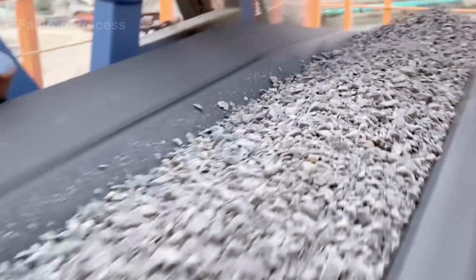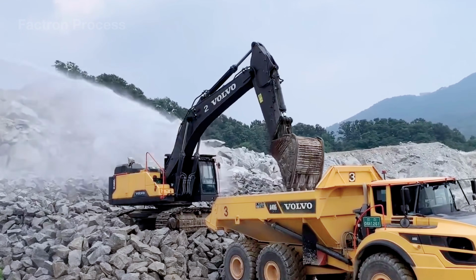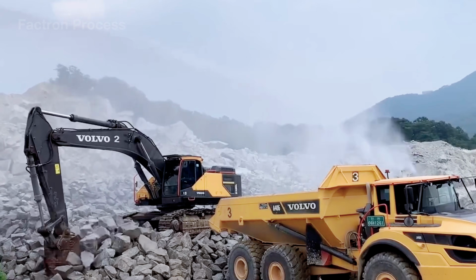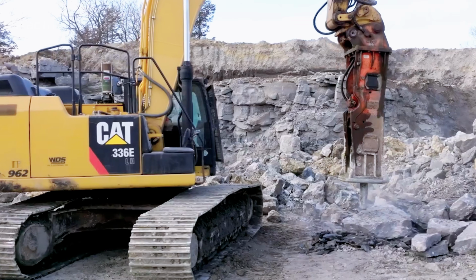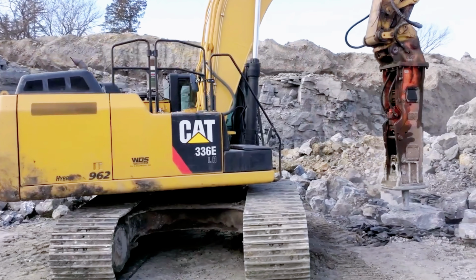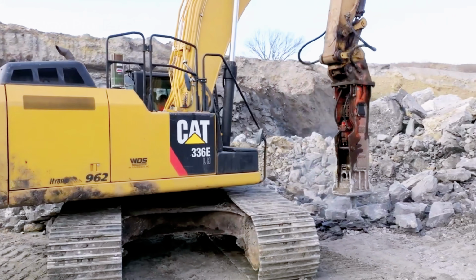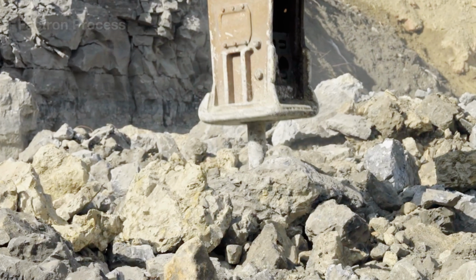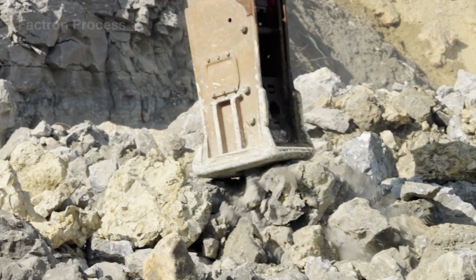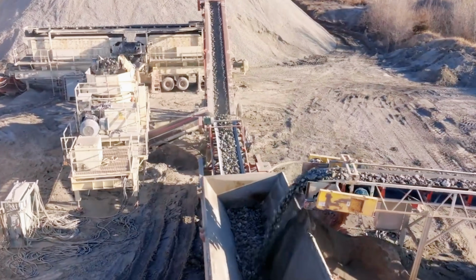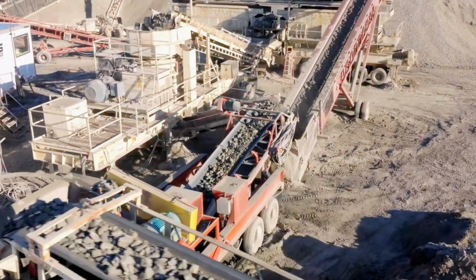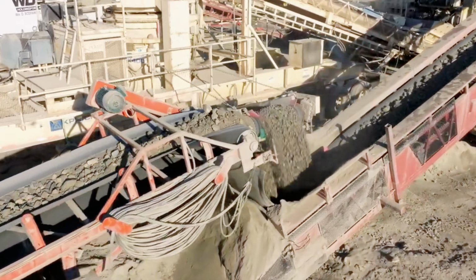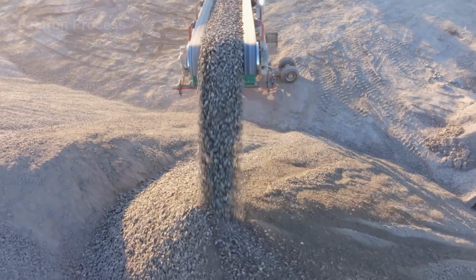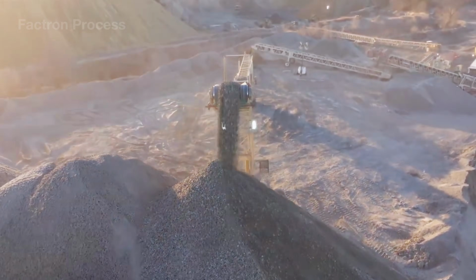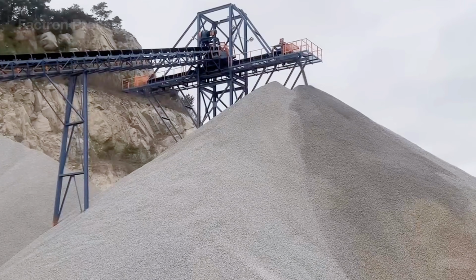Ore that reaches the required size is mixed with water and fed into a horizontal ball mill, approximately 4 meters in diameter. Inside the rotating drum, thousands of steel balls are continuously lifted, dropped, and driven into the ore, grinding the material to below 200 micrometers. A hydrocyclone system then classifies the mixture by particle size and mass. Coarse particles that fail to meet the standard are returned to the mill, while the uniform fine fraction continues to the flotation stage.